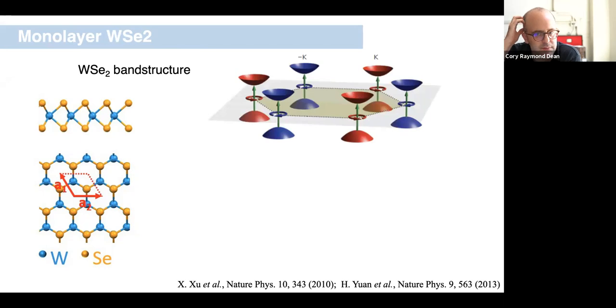Okay, so this though is a good representative system for any of the TMDs. They all have basically the same kind of structure and some version of the same band structure, more or less. The idea here is that, as viewed from the top in the bottom left cartoon, we again have something that looks like a honeycomb lattice. But it's not a honeycomb lattice in the same way that graphene is, in the sense that there is a difference in the A and B sublattice sites in this system.